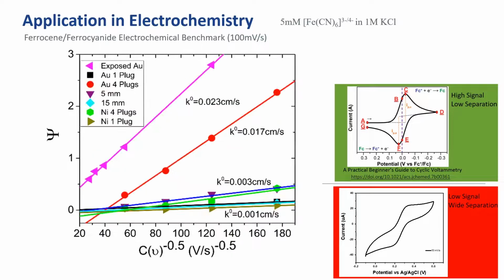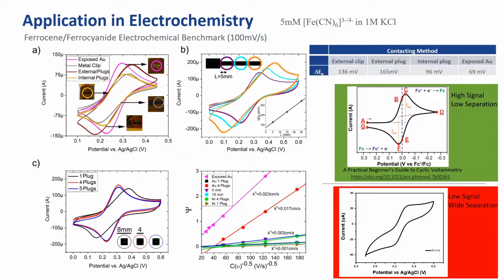Finally, when the electrochemical kinetics are extracted from the peak separation and intensity for a number of scan rates, we see that the system with the lowest access resistance, the internally contacted structure with 4 plugs, demonstrates kinetics competitive with exposed gold of a similar footprint area. This demonstrates the potential for the innate high surface area of LIG if the access resistance challenges are surmounted.